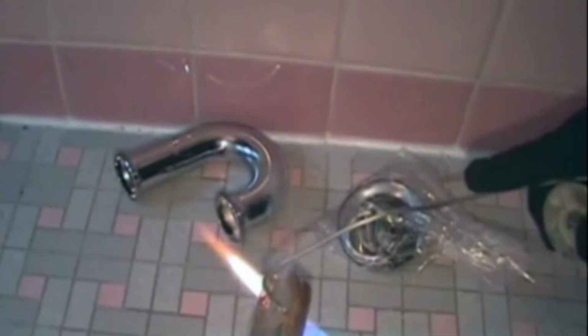Right, he is intentionally trying to create a massive, thick blob of semi-melted lead encompassing the entire exterior of the connection. The choice of the 60/40 alloy is paramount here. We discussed how modern 95/5 solder turns into a watery liquid almost instantly. Yeah. 60/40 lead operates differently. Because it is close to a eutectic composition, but not quite perfect, it possesses an incredibly broad plastic range. Okay, so it gets mushy. When heated, it doesn't immediately liquefy. It transitions into a thick, mushy, semi-solid paste. It behaves exactly like heavy metallic clay.